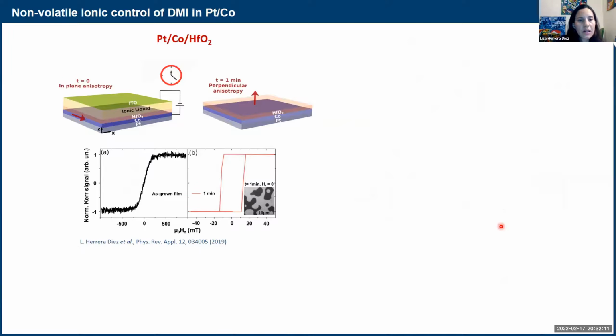Okay, so let me now tell you a little bit more of our own work on magnetoionics. I mentioned already our interest in controlling the properties of the bottom interface of our ferromagnetic layer, with the idea of controlling DMI. Here we went for a stack which has platinum, cobalt, and hafnium oxide. We put the ionic liquid on top and applied the voltage. We started with a layer that had in-plane anisotropy, and then after applying the electric field, it went to a perpendicular state very nicely, with very nice domains.